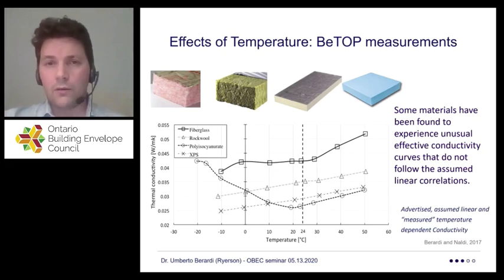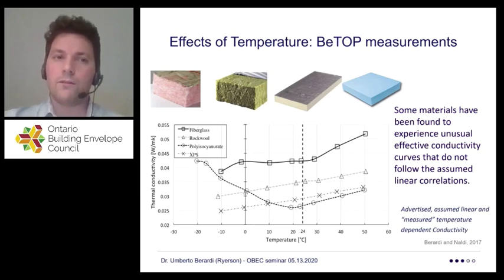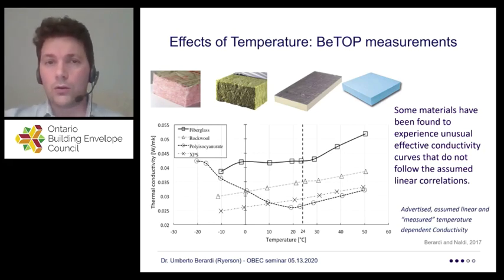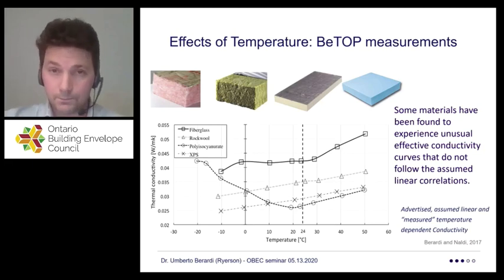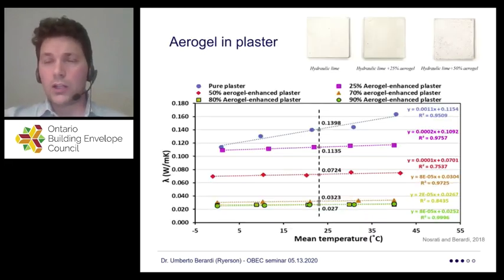And what have we found? We have found that XPS, rock wool, and fiberglass have pretty linear behavior. Polyisocyanurate tends to have less linear behavior, or a non-linear behavior, at temperatures below 0. I'm not going to spend a lot of time, and I don't want you to focus too much on the values, but on another aspect. And the aspect is that whenever we take measurements at 20 or 23, 24 Celsius, we are not necessarily taking a good photograph of the behavior of a material in the field. When I say in the field, it means these products are going to be affected by temperature quite a lot. Just to give you a sense, this is actually true for every material.